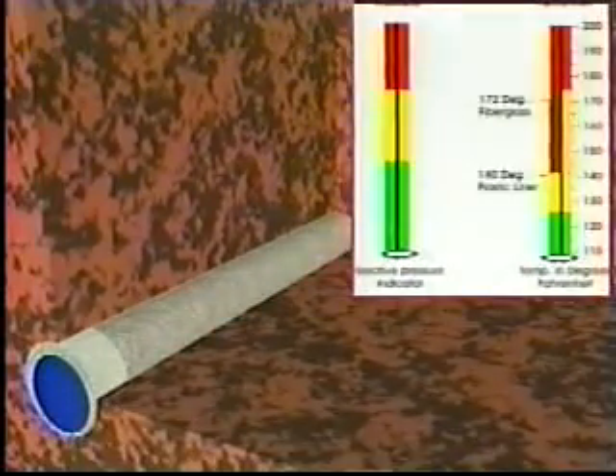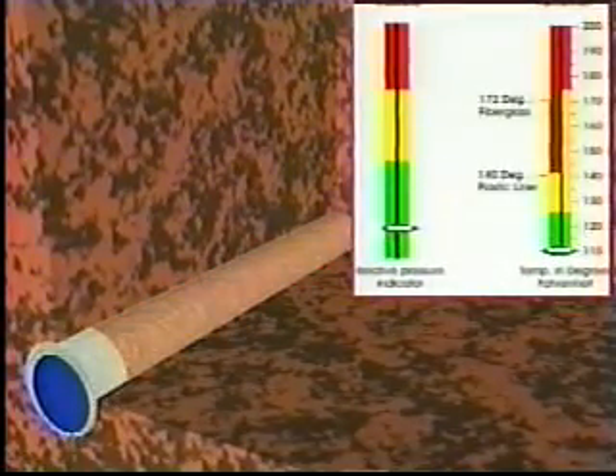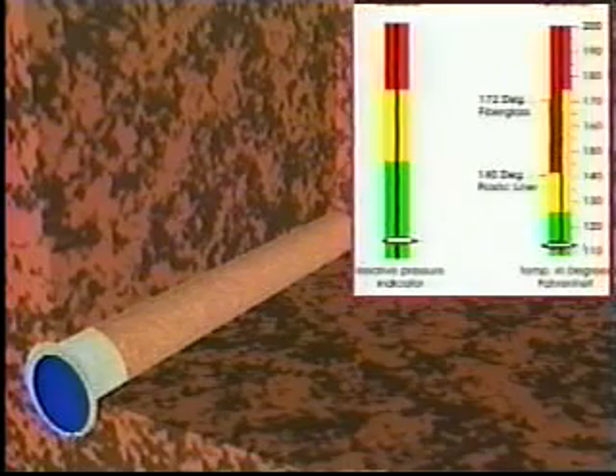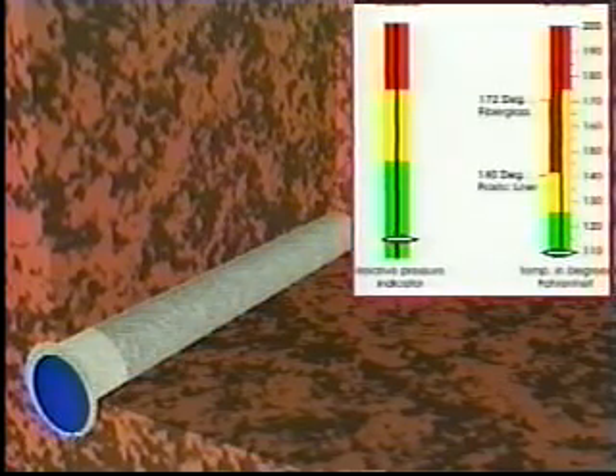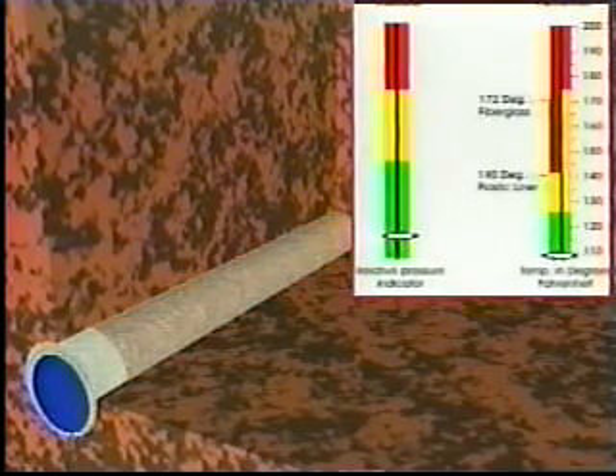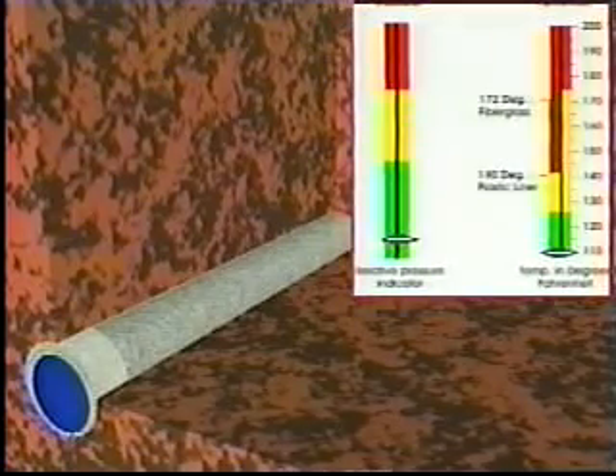We begin here and begin to pump in the cellular concrete grout. Note that the wastewater-filled slipline pipe stays on the bottom of the old concrete pipe. No great pressure was involved, and the heat of hydration was 110 to 120 degrees Fahrenheit, well below the heat distortion temperatures of 140 and 172 Fahrenheit for plastic and fiberglass liners, and far below the 180 to 200 degrees Fahrenheit developed by heavy grout.